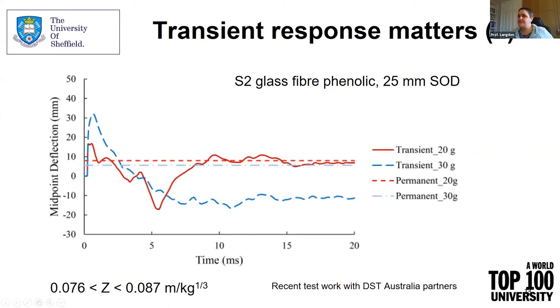However, if you look at the transient responses now, these are very different to what we were seeing a moment ago. So the blue line, which is at 30 grams, is quite similar to what we saw for the 40 and 50 gram tests at a slightly larger standoff. But at 20 grams, you see that the response is significantly different. In this case, the peak negative rebound displacement is greater than the original peak positive displacement.